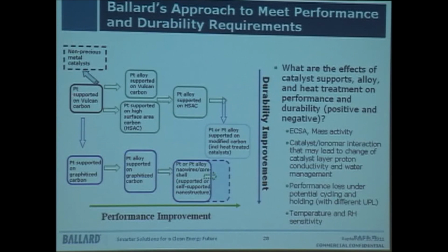However, when we put this into real-world application, we quickly found that either performance or durability could not satisfy our requirement. For durability, we gradually changed to a graphitized carbon-based catalyst. You will know that changing regular carbon to graphitized carbon significantly improves the stability, and we continued working on performance improvement. At the same time, we also changed to a platinum alloy catalyst, either on the same carbon or on a high surface carbon, to further improve performance.